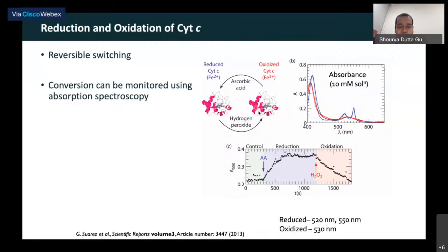Now, since it's a redox reaction, you can always reduce it and oxidize it. Now, for reducing it, you add a reducing agent like ascorbic acid, and for oxidizing, you add a chemical like hydrogen peroxide. Now, this is typically what you can do. This horizontal axis is the time, and vertical axis is the absorption at 550 nanometers. So higher the absorption, more the reduced cytochrome C that you have. So till this point, we did not add any chemical. At this point, we're adding ascorbic acid. So the absorption goes up, so it becomes more and more reduced. And at this point, we are oxidizing it. So it reduces in intensity, right? So this is typically what you can do.